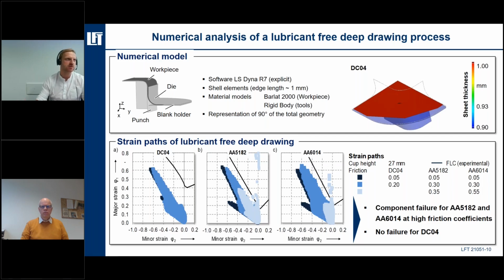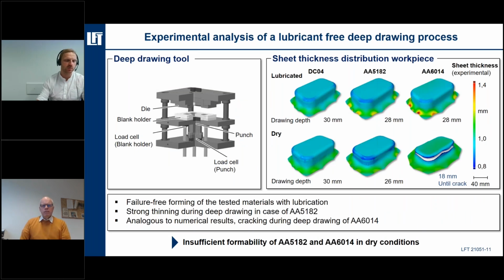So now the task for us was to generate a surface coating with friction coefficients under 0.3 in order to enable a failure-free forming without any lubricants. In the first step, to verify the reliability of the FE simulations and the feasibility of deep drawing processes, rectangular cups have been formed with and without lubrications. For this purpose, a deep drawing tool, which can be seen here in the upper left corner, was used, which mainly consists of a die, a blank holder, a punch, and load cells in order to measure the maximum punch forces and blank holder forces.